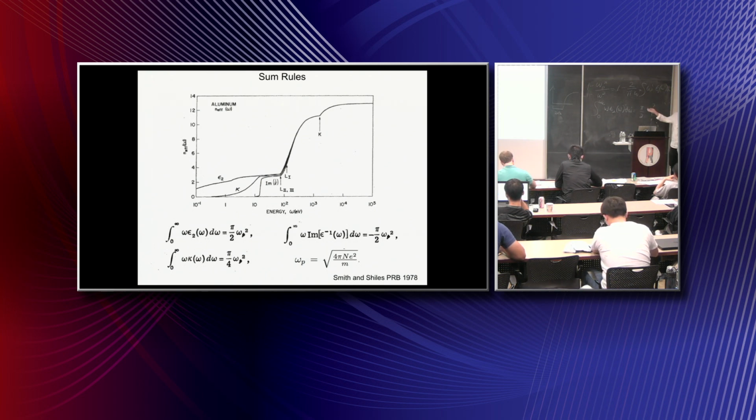So what this says is that there's an integral on the dissipative part of the dielectric response, a first moment sum rule, which says that with some constants it's related to the plasma frequency squared, where the plasma frequency squared is, as I wrote down over there, the density of carriers divided by their mass. Okay? Now, this is an integral which is going up to omega c.